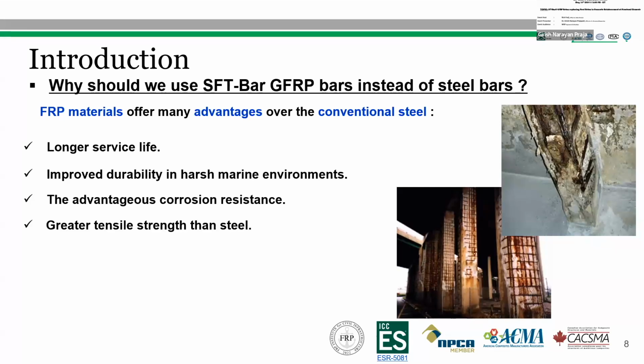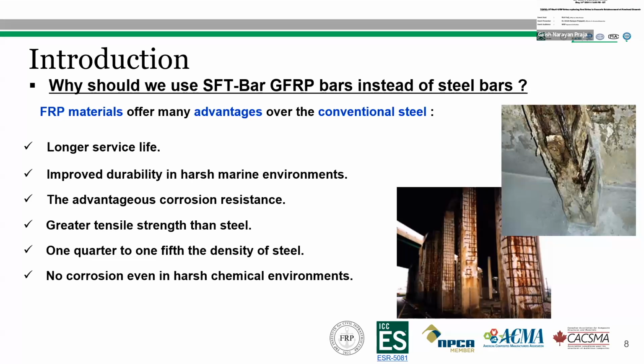The tensile strength of FRP bar is around 2 to 3 times more than that of the steel bar. I'm talking about the glass fiber reinforced polymer bar. If you consider carbon, it has more tensile strength compared to the steel bar. However, it is lightweight because of the low density compared to the steel bar, and due to the corrosion resistance, FRP bars are good for the harsh chemical environment in Canada. Because of the cold, we have to put alkaline salt during winter, and it is also neutral to electrical and magnetic disturbance, useful for applications such as airports, military applications, and MRI rooms in hospitals.